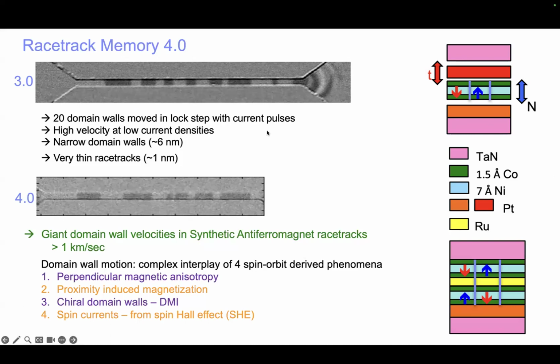And on the left-hand side, you can see optical images of racetracks, which are microns wide in order to detect the domain walls. But we take an image using something called the magneto-optic Kerr effect, in which the polarized light is reflected from the surface. The planar polarization is rotated to the left or right, depending upon the direction of the magnetization in the racetrack. And then we can detect the motion of these domain walls by applying a current pulse, measuring an image of the domain walls, applying another current pulse, and seeing how they've moved. So we can detect their velocity. However, these optical techniques, well, they have enabled us to develop all this interesting physics.